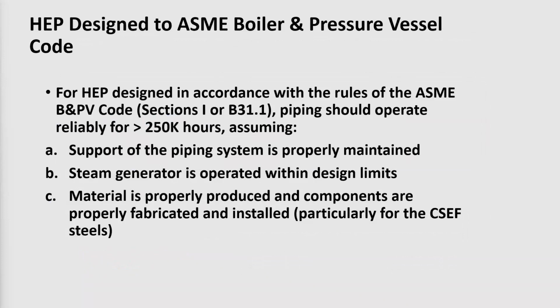One thing to keep in mind too, in terms of defining the life of these piping systems, for those systems that have been designed in accordance with the ASME boiler and pressure vessel code, for example, the components should operate reliably for at least 250,000 hours, depending on the material type. But this assumes, first of all, that the support of the piping system is properly maintained, that the steam generator operates within design limits, and the material from which the piping system is fabricated is properly produced, and the components are fabricated and installed properly.